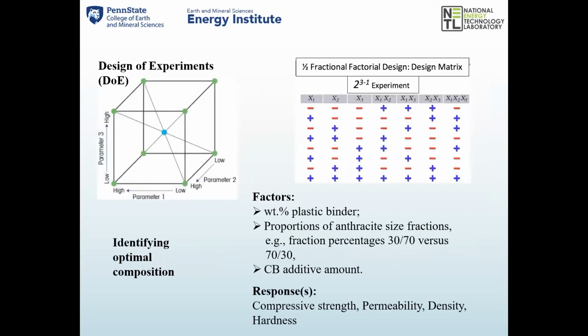The form factors will be determined on the use and strength. So this just gives you an idea of our design of experiments. The factors, we're employing a fractional factorial design matrix. The factors are the weight percent of the binder, the proportions of anthracite size fractions, and carbon black additive amounts. Our responses are compressive strength, permeability, density, and hardness.